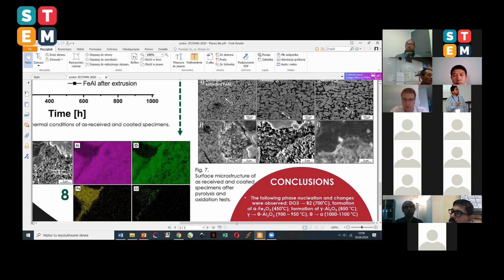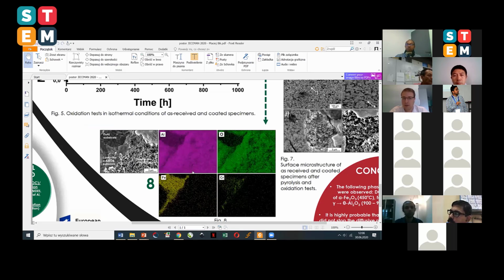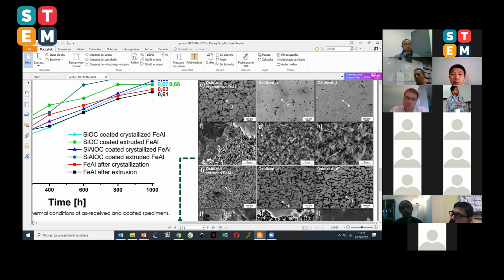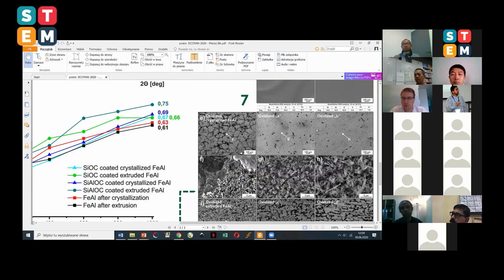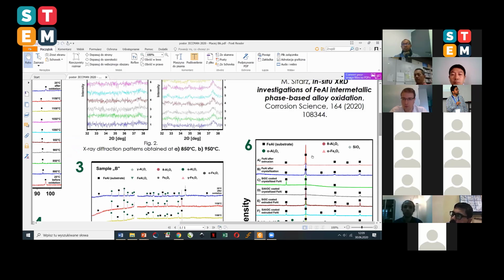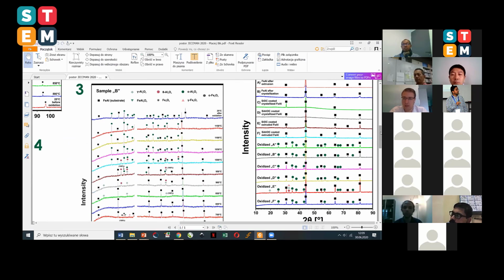So here, I would like to move on to the 8th figure, with EDS mapping analysis, which fully confirmed the formation of alpha alumina. The top layer consists of needle-like alpha alumina, and the layer below is a lump-like alpha alumina subscale. It is quite a usual phenomenon for these alloys to create a multi-layered scale, because in the beginning, metastable phases are created because of outward cation diffusion, and then alpha alumina is created because of inward oxygen diffusion. So in this case, it seems that our coatings slightly blocked this inward oxygen diffusion, and the spallation was blocked, and also here we could still see the theta phase in our sample.